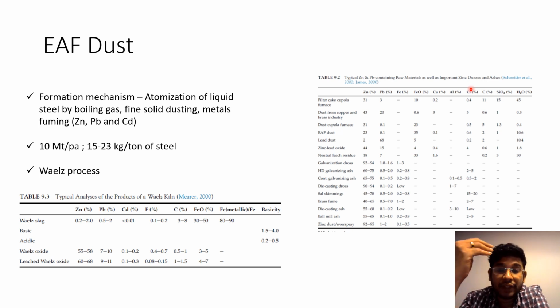And when you do this Waelz process, what you have is the composition of the end product indicated here. So this is the Waelz slag, and then of course you have a slagging process, the pyrometallurgical process, and this is the main oxide you get from the Waelz process, okay? Then they also have what's called leached Waelz oxide. So the only difference you see here is the reduction of fluorine content. So they just have a washing process to remove the halogen.